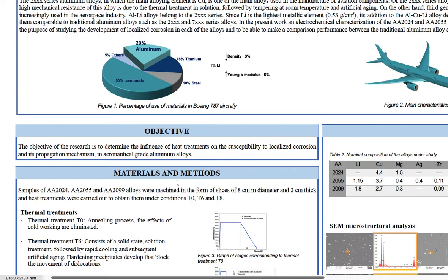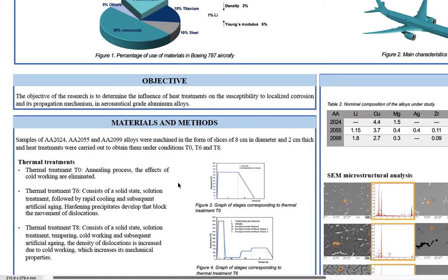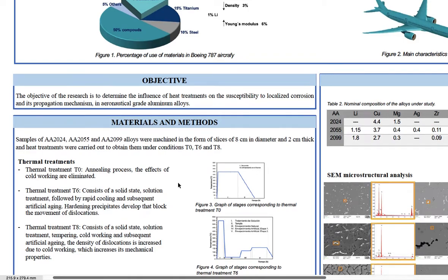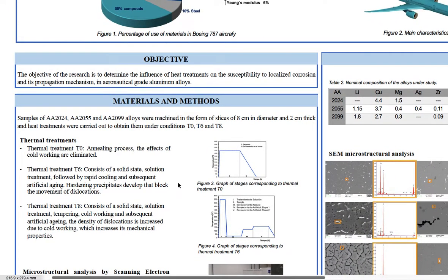The alloys under study were obtained in the form of a bar from which they were machined to obtain samples in the form of slices of 8 centimeters in diameter and 2 centimeters thick. These samples were subjected to heat treatment to obtain the three alloys, 2024, 2055, and 2099, under three heat treatment conditions: T0, T6, and T8.